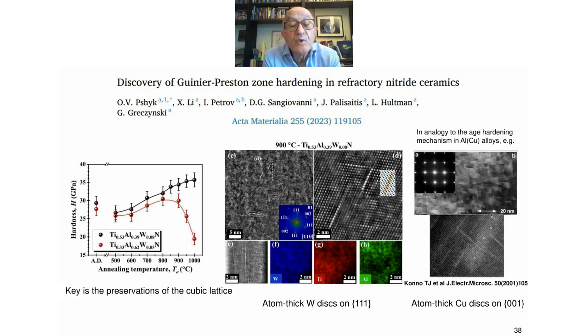Here we zoomed in, and what we saw is all of these single-atom-thick discs of tungsten on 111 planes, and they're analogous to the Guinier-Preston zones that were discovered in the 1930s by Guinier and Preston in soft aluminum-copper alloys, demonstrated to the right. For the aluminum and copper alloys, these occur on 100 cubic planes. In our coatings, they appear on 111. So this is the first time, to our knowledge, reported for refractory nitrides. Next slide.